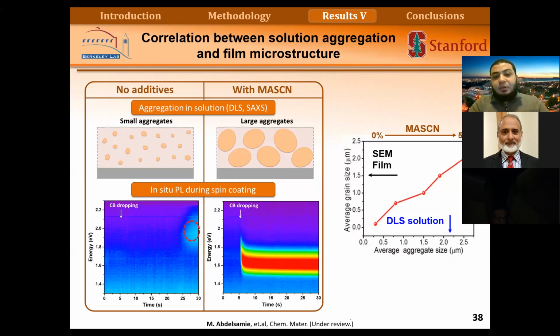So what we have applied for this material, without additives on the left and with additive on the right. What we have seen is aggregation in the presence of additives. If you use additives, we have very large aggregates in solution. And this also affects the process during spin coating. We found during spin coating, if we don't have additives, we form very confined crystals. And we know this from the confinement of the PL emission.